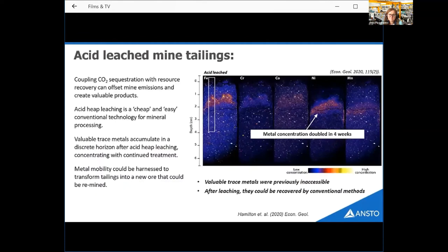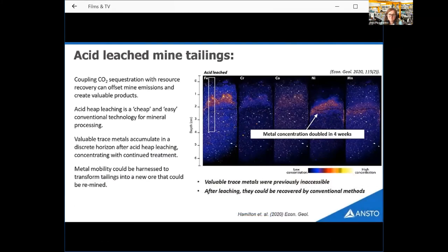Finally, it was time to try that acid leaching. So we set up a series of 50 ml syringes, packed them with tailings, and I irrigated them with sulfuric acid every day for a month, simulating a heap leaching process, which is pretty conventionally used in mining. Pretty soon, I noticed an orange line forming just below the surface, and it migrated downwards over time. That was iron oxides precipitating out at the neutralization front. So above that line, acidic conditions are dissolving all that material. Then we see iron and transition metals crashing out, and below that, the material was pretty well unreacted and still very alkaline.